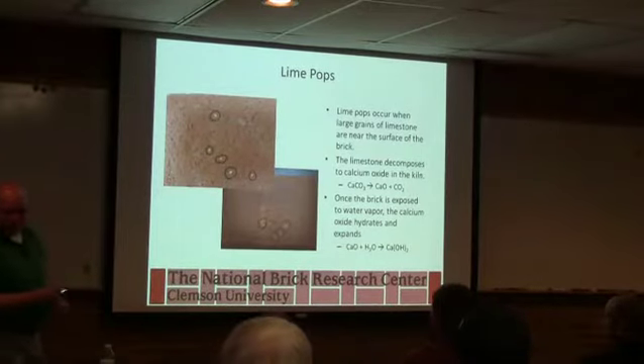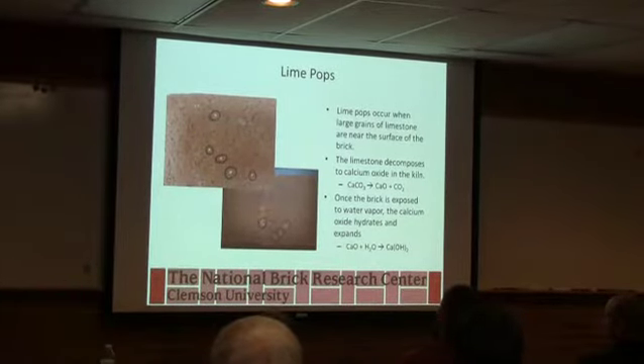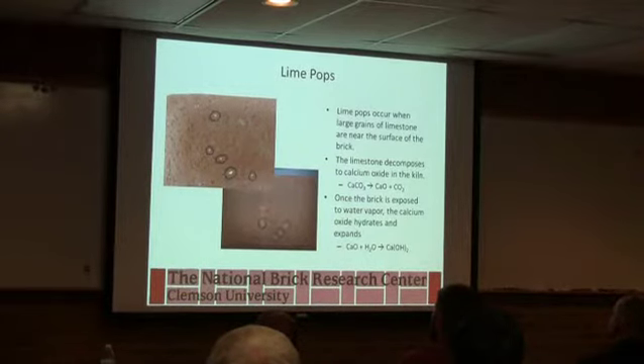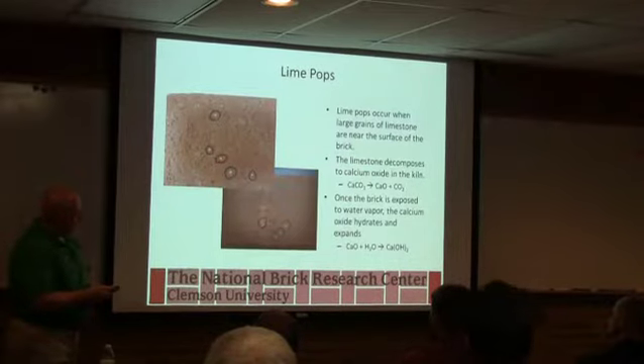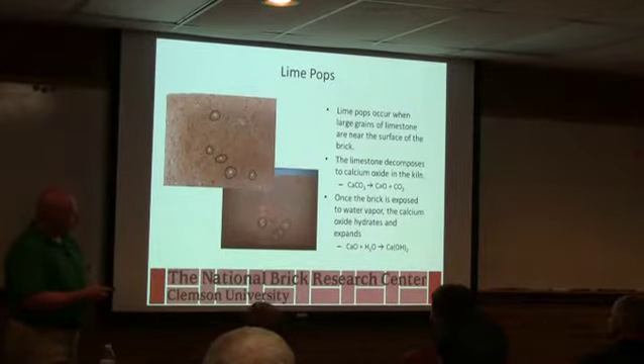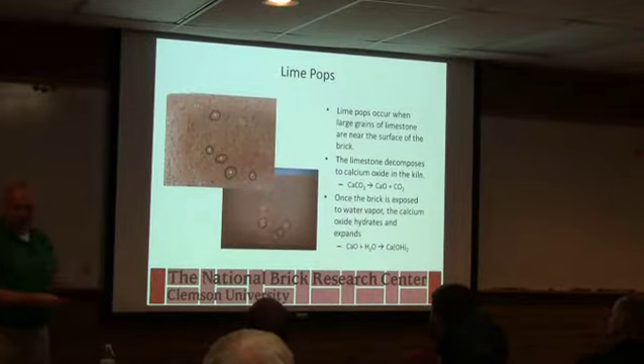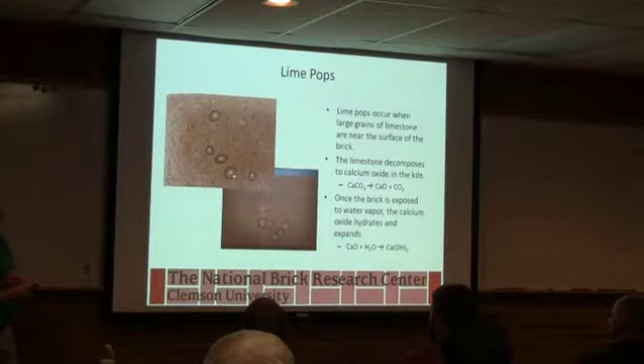So this is a lime pop. They typically happen after the brick has left your yard, and unfortunately, most of the time they're noticed they're already in a wall. So what that was is a limestone grain that made it through the process, ended up near the surface of the brick. And so I start out with calcium carbonate, and when I heat it up, I get calcium oxide plus carbon dioxide. Calcium oxide doesn't like to be calcium oxide. It will pick up any moisture it can, and it will form calcium hydroxide, and it expands, and that's what makes it pop.